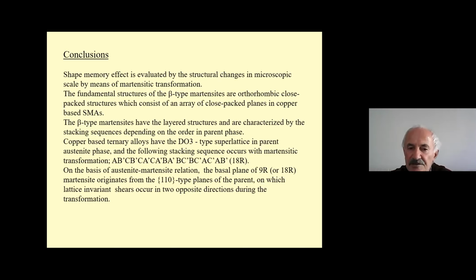The fundamental structure of beta-type martensites are orthorhombic close-packed structures, which consist of an array of close-packed planes in copper-based shape-memory alloys. The beta-type martensites have layered structures and are characterized by the stacking sequences depending on the order in the parent phase structures. Copper-based ternary alloys have the DO3-type superlattice structure in the parent austenite phase, and the following stacking sequences occur with the martensitic transformation. Sequences are AB, CB, CA, CA, BA, BC, BC, AC, and AB for 18R martensitic structures.